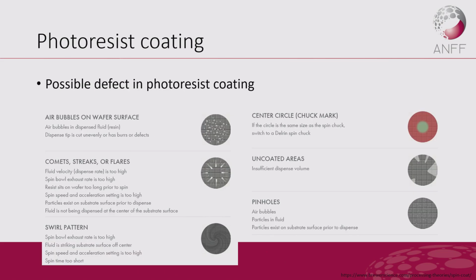After you coat the photoresist, you can do a visual inspection to see if there are any defects in your coating. Sometimes you will have air bubbles if you don't remove the moisture or water on the surface, and you will have comets or flares because there are particles on your substrate you didn't clean well. Or you have some uncoated areas, or you applied two layers of photoresist, or pinholes. There are so many things that can go wrong, but if you have an even and perfect photoresist coating, you can move on to the next step.